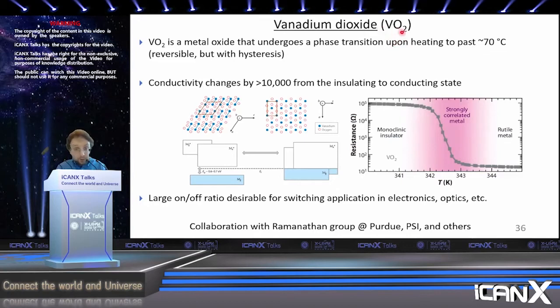So VO2 is a metal oxide that's been known since about 1960 or 1961 to undergo a phase transition when you heat it past about 70 degrees Celsius. And this is a reversible transition, but with a hysteresis. And this is a very dramatic phase transition in that, for example, the DC resistance changes by 4 orders of magnitude across this transition. And you can, of course, go back and forth many times. The crystal structure changes, the band structure changes completely. And so this very large on-off ratio in this material is highly desirable for switching applications in electronics and optics and so forth.